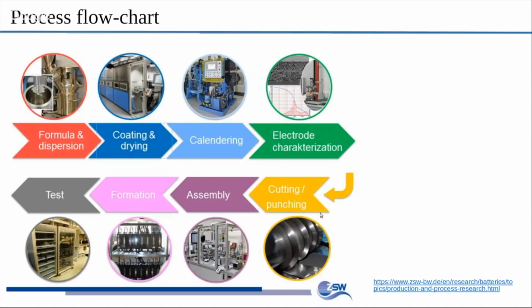And then you cut it and punch it to the exact size you want for the 18650s. And then once you cut it, you assemble it into a jelly roll that we saw in the previous slides. You have a jelly roll in a cylindrical format, and then you add electrolyte into that at this stage. And then you have the formation. You initiate the cell to a certain voltage, and then you test it. Out of a batch of 100 cells, you take a few of them out, make sure it gives you the right voltage, right current, power density, energy density, and then you ship the whole batch. So this is the process flow chart.